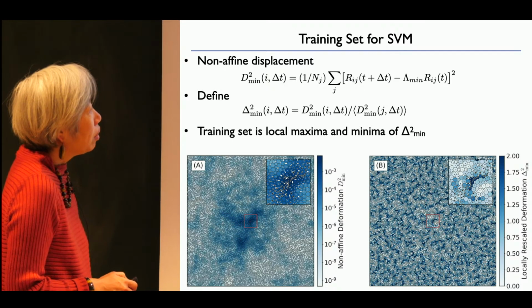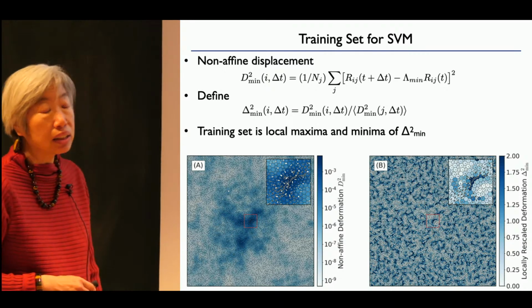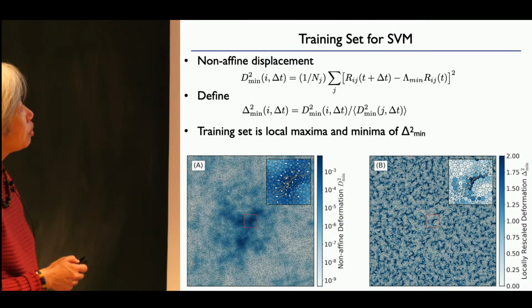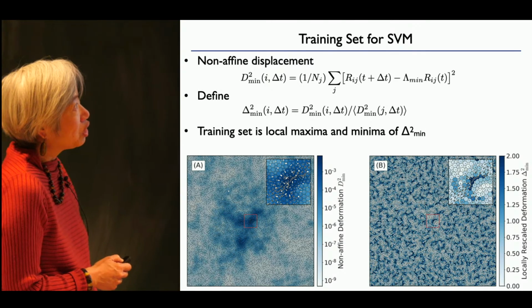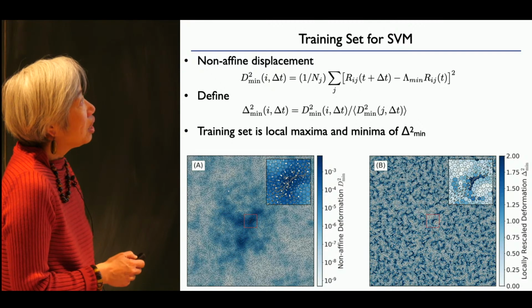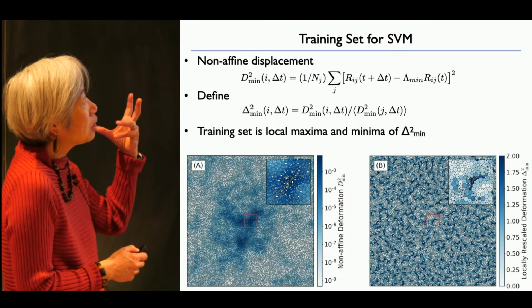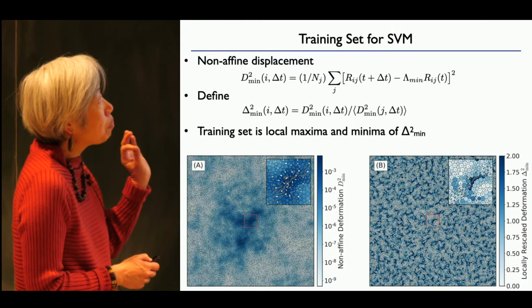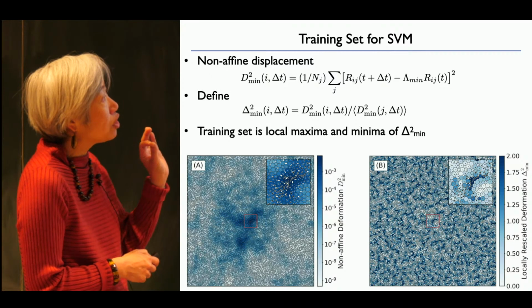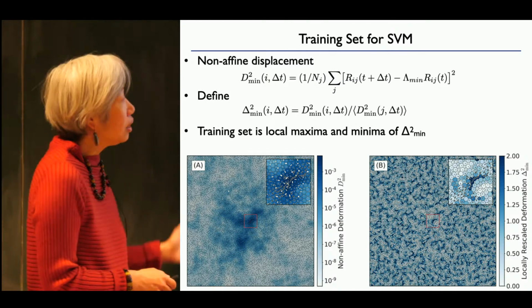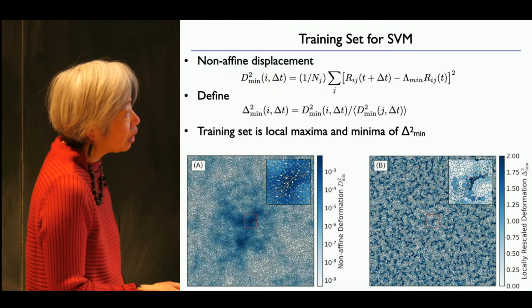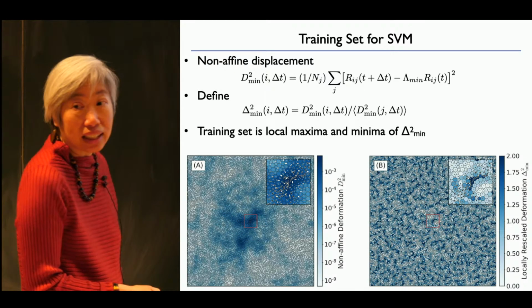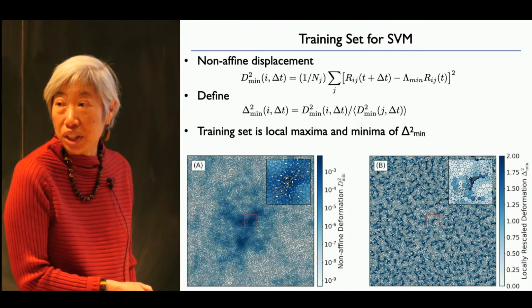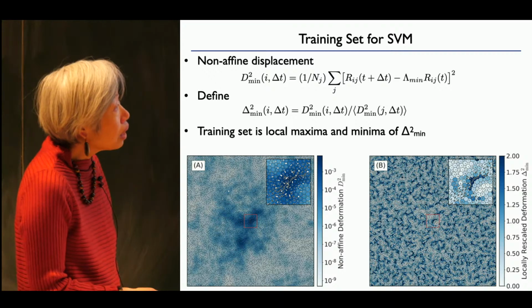So to get rid of the power law tails here, what we do is we look at this quantity, we call it delta squared min, which is basically just d squared min, this non-affine displacement for my particle i, divided by the average over its neighbors. This eliminates the elastic tail, and if you look at delta squared min, it looks like this. Okay, so it's now homogeneous across the whole system.